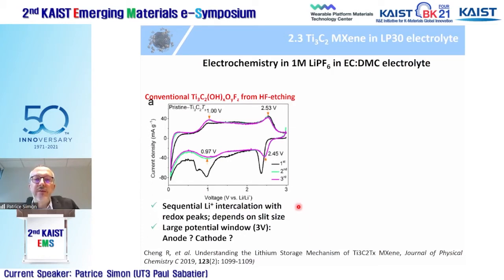electrochemical characterization of these materials in lithium ion battery electrolyte, LiPF6 in EC-DMC electrolyte. So this is first a conventional MXene prepared from HF etching in what we call LP30 electrolyte, this LiPF6 carbonate-based electrolyte. What you see is that for this HF prepared MXene you have a lithium intercalation with different redox peaks. The position of the peaks depends on the slit size of the MXene. However, you can see that this lithium intercalation occurs over a wide range of potential. So it means that this is not even a good anode, not even a good cathode, because for a negative electrode you need to keep the potential as low as possible, and for a positive, as high as possible. However, here it's not clear whether it's an anode or a cathode.